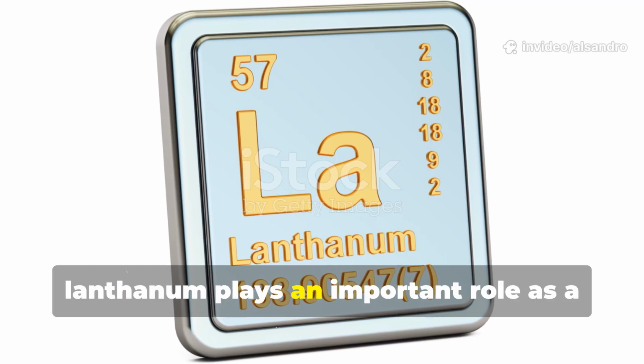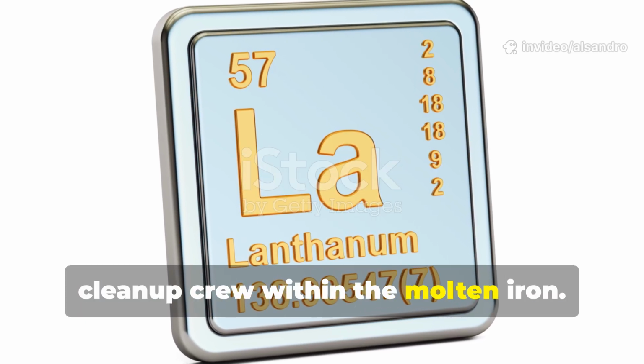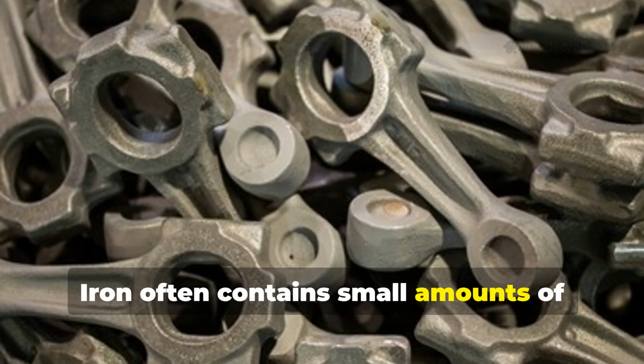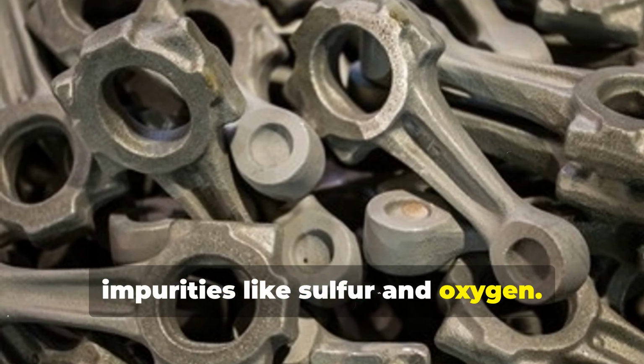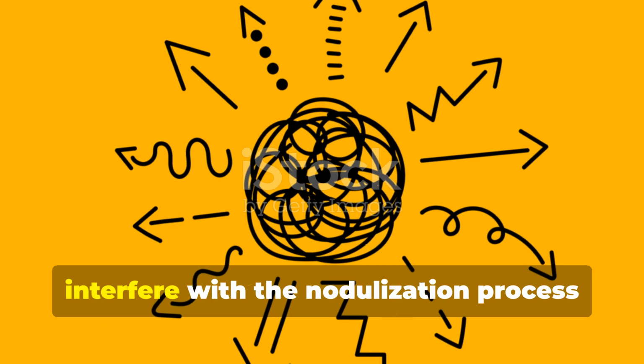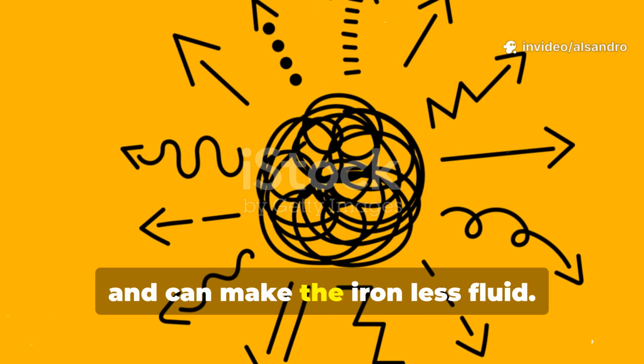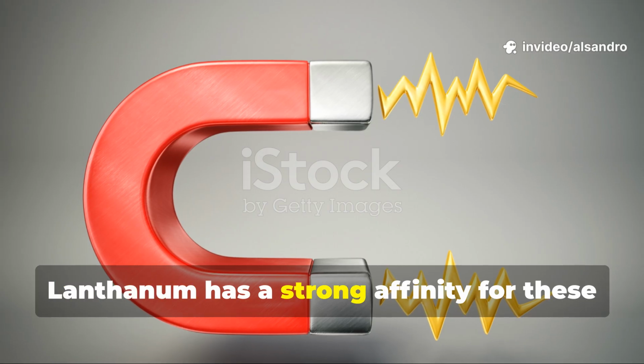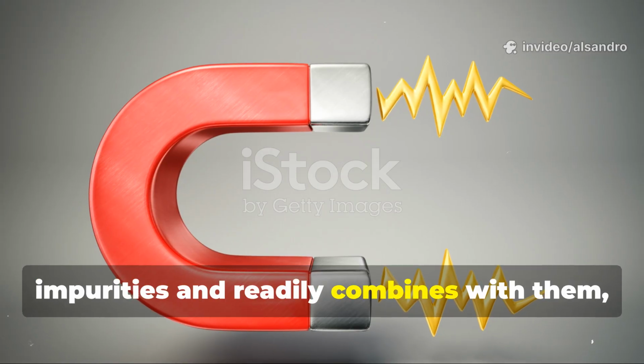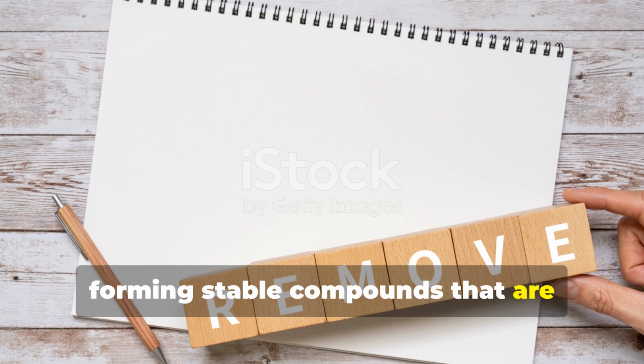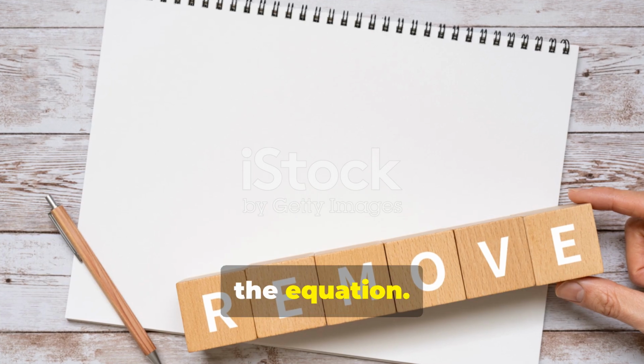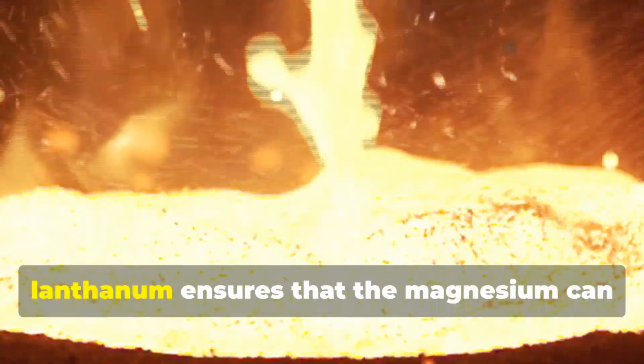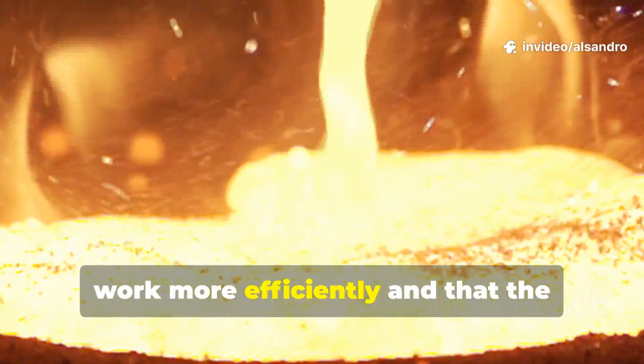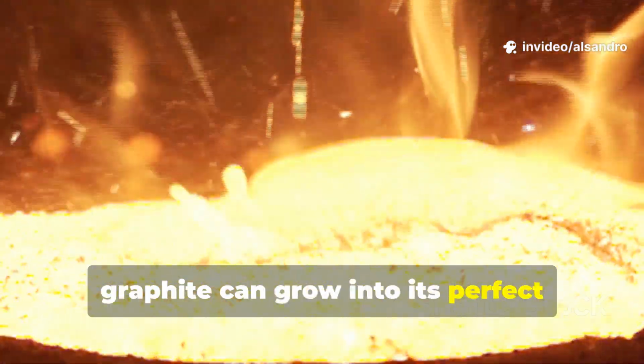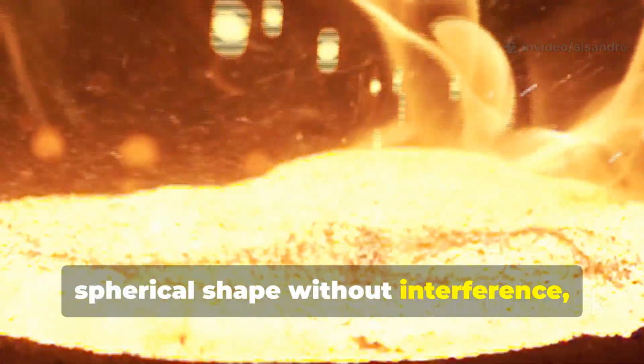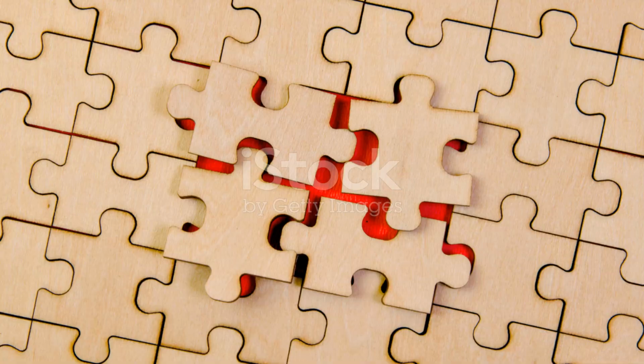Furthermore, lanthanum plays an important role as a cleanup crew within the molten iron. Iron often contains small amounts of impurities like sulfur and oxygen. These elements are trouble because they interfere with the nodulization process and can make the iron less fluid. Lanthanum has a strong affinity for these impurities and readily combines with them, forming stable compounds that are effectively neutralized and removed from the equation. By cleaning up the melt, lanthanum ensures that the magnesium can work more efficiently and that the graphite can grow into its perfect spherical shape without interference, further reducing the risk of defects.